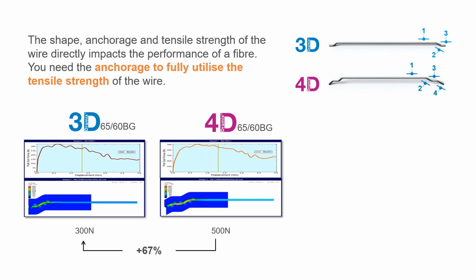As you can see in the illustrations below, which are of a pull-out test, we have our 3D and 4D 6560 BG fibres, which are at the same length and diameter and therefore aspect ratio. As you can see with the 4D fibre, we're using a higher tensile strength wire because we have better anchorage, so it takes more force to pull the fibre through. We don't want the fibres to snap, because if we snap the fibres, we're going to get brittle failure.